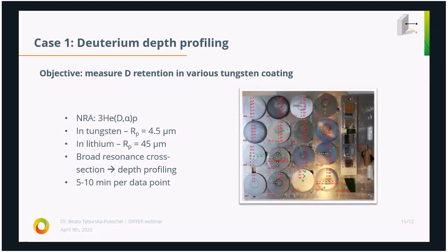Case one: we currently use ion beam analysis mostly for deuterium depth profiling for diffusion purposes, and we generally use nuclear reaction analysis. Our beam coming from the accelerator is helium-3. We want to detect deuterium. What we measure are alpha particles and protons. When we perform this experiment in tungsten, our penetration depth is maximum 4.5 micrometers.